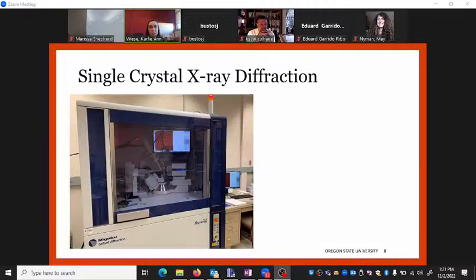So one of the main ways that I do this after I make one of these new materials is I use single crystal X-ray diffraction. This is a picture of our instrument that we have here on campus. Basically what I do is I isolate one single crystal out of my sample. And this part is probably the most tedious because you have to look for a really good single crystal that's not overlaid with others.